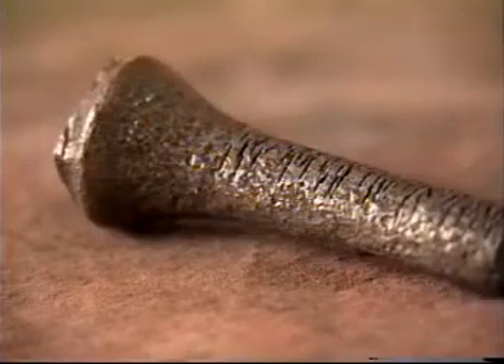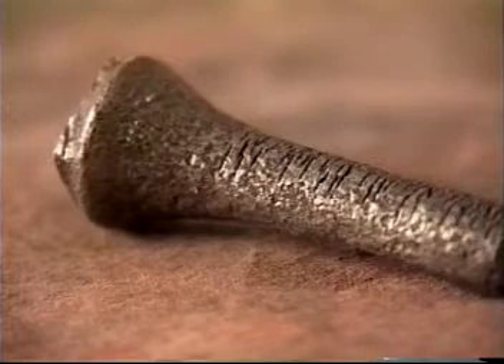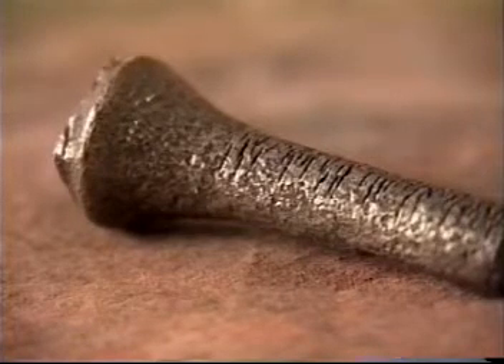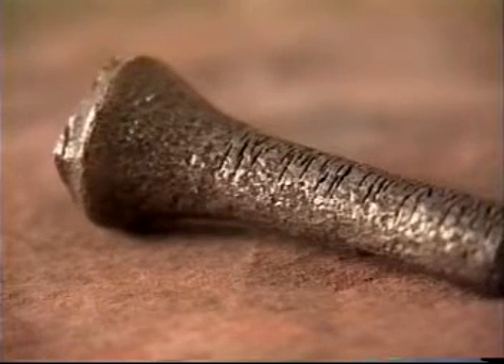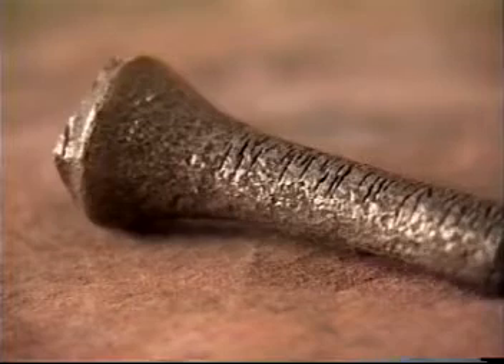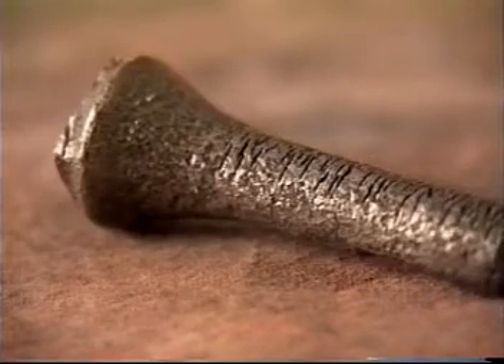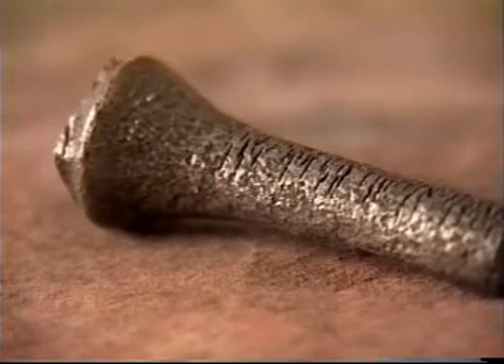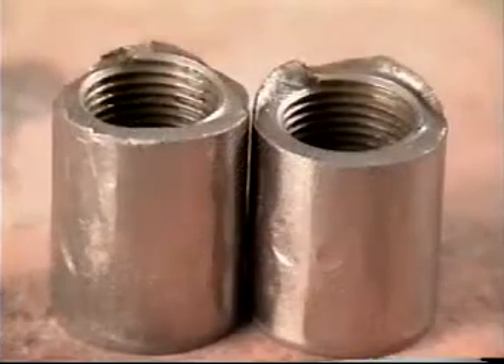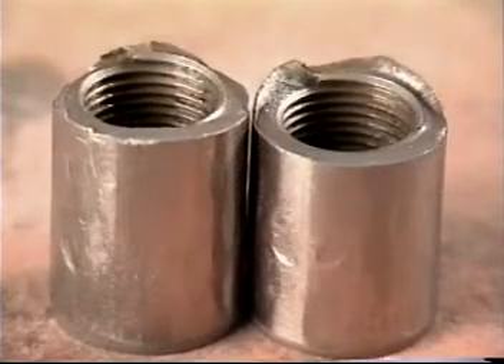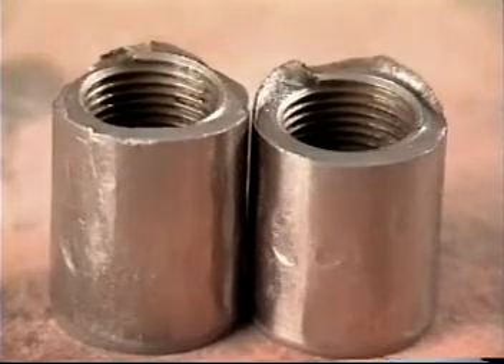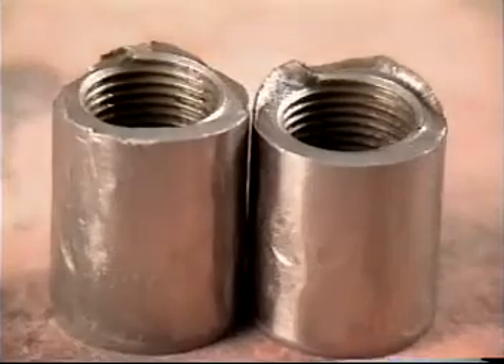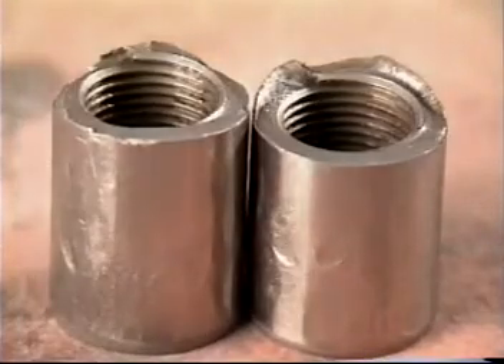Tubing slap creates a multitude of problems. Compression of the rod string causes stress cracks that are close to the upset. These types of stress cracks usually do not extend all the way around the rod, but they always lead to rod failure. Tubing slap also causes couplings to fail. Couplings that incur stress cracks from this type of damage will nearly always fail in a 50-50 configuration.